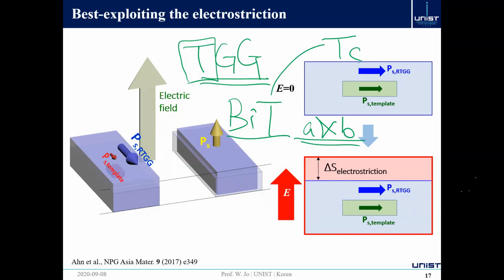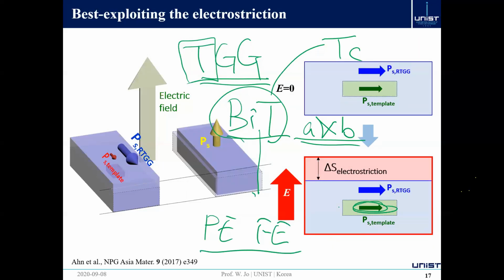That's why during cooling, this material transforms from paraelectric to ferroelectric, so that it already has a spontaneous polarization along the a direction or b direction, in the in-plane direction. So once the Curie point of this lead-free material is reached during cooling from high temperature, this lead-free material automatically polarizes along this direction. That means this template can hold the entire spontaneous polarization in the lead-free piezoceramics, so whenever you try to switch this spontaneous polarization of the lead-free material, once you remove the electric field, it goes back. That gives you really, really high strain.